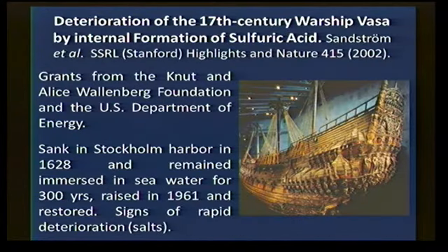Another example is a superb piece of work which was done on this particular warship here. This is a warship which sank in the harbor of Stockholm more than 300 years ago. And it was recovered back in 1961. It was taken out of the water, out of the seawater, and it was exposed in a museum. And what happened here in that particular case is that rapidly there were signs of deterioration. There were growth of salts and appearance of acidity over the boat. So the warship was rapidly deteriorating in the museum.